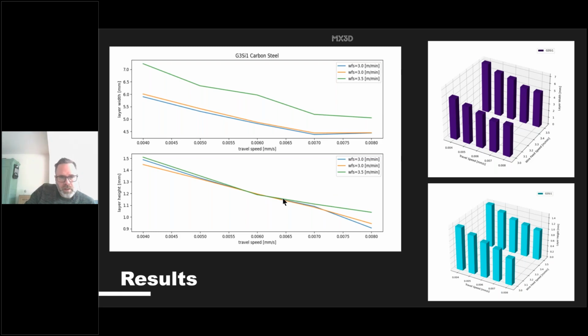And surprisingly, the wire feed speed didn't do much to the layer height, as you can see in this figure. Other than that, everything looks as expected. If you increase the travel speed, the layer width decreases, and also the layer height.